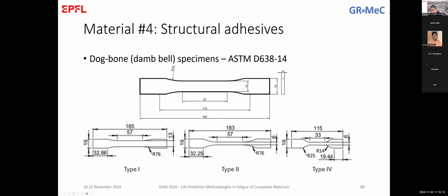And it says also somewhere in the standard that in cases where you have tab failures, so failures that are initiated because of the gripping of the machine in this region, or you have other types of unwanted failures, you can use specimen type 2 or specimen type 4. Type 2 actually is the same as specimen type 1, but has a higher radius here and ends up with a smaller region in the middle to allow having a region here with lower area that will promote the crack at this region.